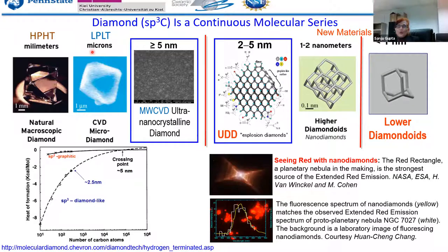1989. And we call it low pressure, low temperature, which is one of my areas of expertise. We can use either hot filament chemical vapor deposition or microwave chemical vapor deposition, and we call them low pressure, low temperature, where you can grow micron size, a couple of hundred microns size diamond, all the way to nano diamond and ultra nanocrystalline diamond, where the grain size is much, much smaller. And we have seen a whole transition in their physical properties, and they're really thriving.